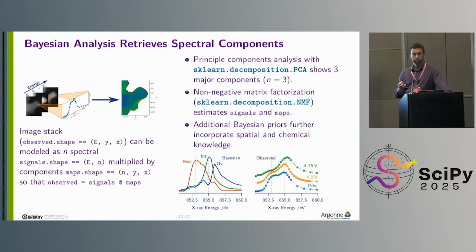All right, and we have maybe two final questions. So, do you have a protocol for masking non-sample components in the operando setup? Yes. So there's 2 steps. One is we moved to a region where there's just no particles. We collected a flat field image and then we move back to where the particles are, and then you just divide those out, and all the things that are coming from like the window or the lithium, that type of stuff, goes away.